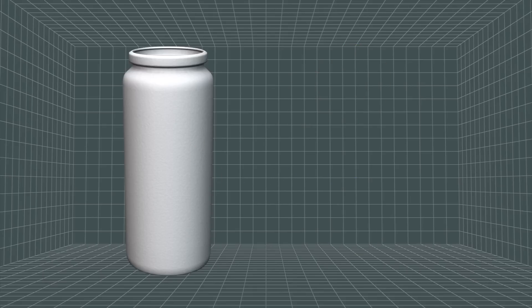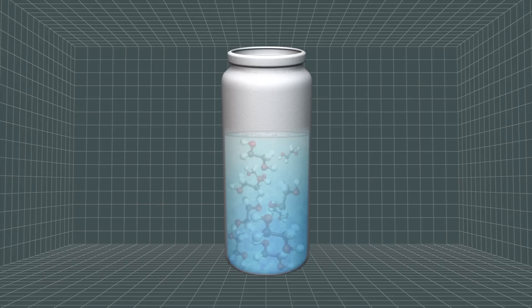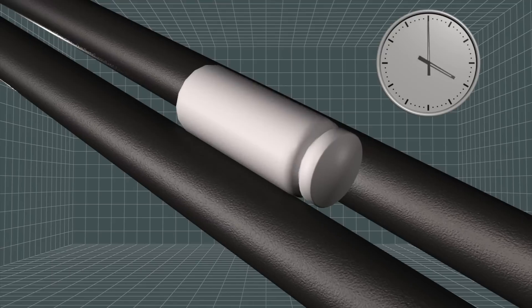To make the ink, nanoparticles of lithium titanium oxide are added to a vial of deionized water and ethylene glycol. Ceramic balls are used as agitators to break down the particles. The mixture is spun for 24 hours.